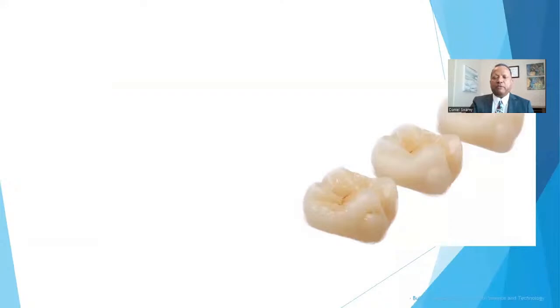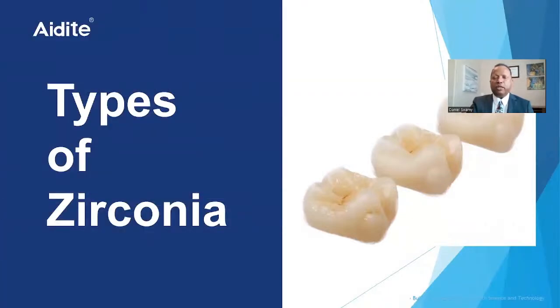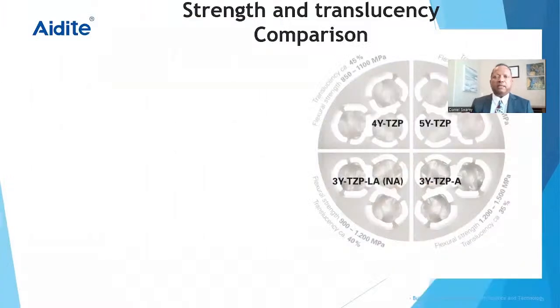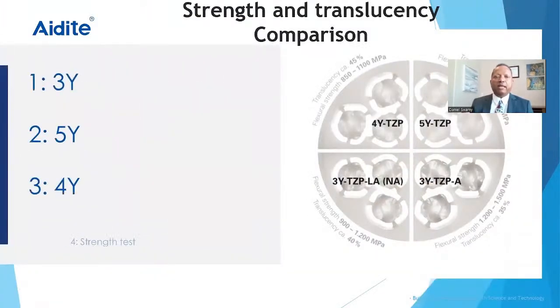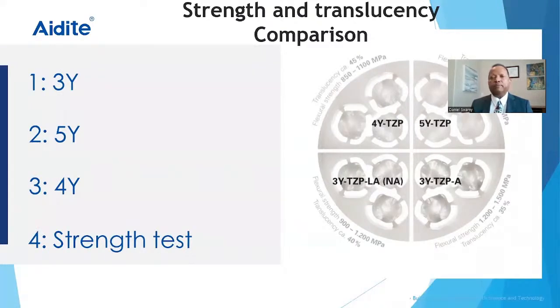Okay, so the types of zirconia that are out in the market, this is just for your information. There is 3Y, 4Y, 5Y, and now we're getting more into the 6Y processes, or formulations. Keep in mind that with the addition of more yttria, you are adding more translucency, but you're losing a relative amount of strength. Now, how strong is strong enough? I would say if you use the classification that's already set by FDA, anything over 800 is useful in our industry.